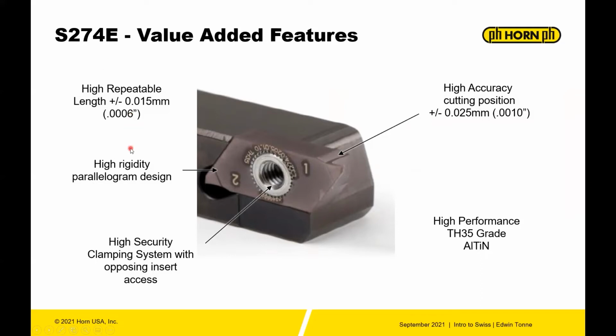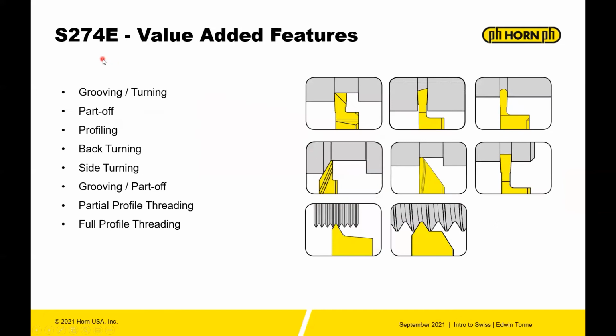High repeatability again, 0.6 on the length. High security clamping, high performance TH35 grade, which is aluminum titanium nitride, and high accuracy cutting position. So due to the clamping, you lose just a few tenths, but it's still very accurate at plus or minus 1/1000 or 25 micron. The E, much of the same operations or applications for our standard product: groove and turn, part off, profiling, back turning, side turning, grooving and part off, partial profile and full profile threading.